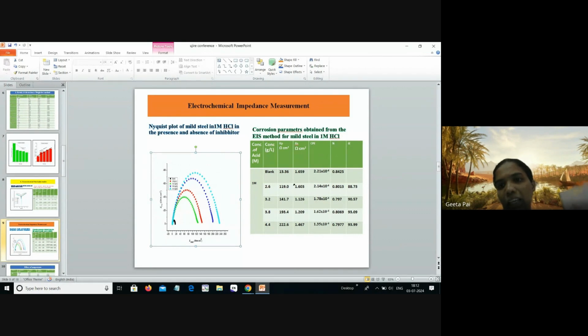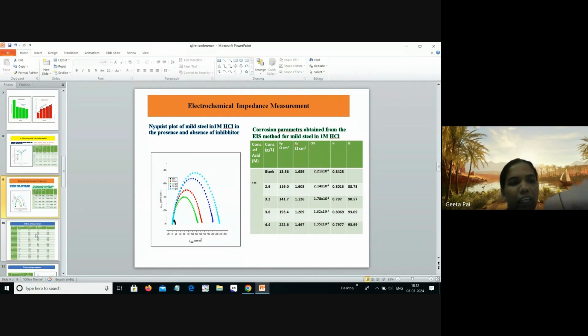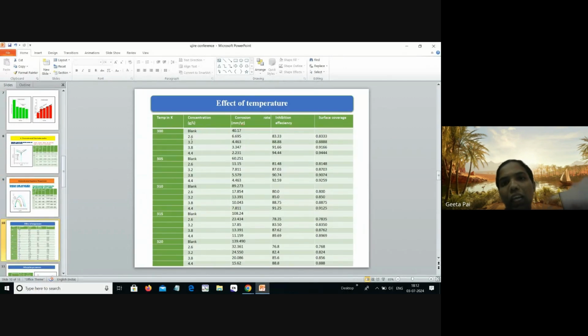Also, as the inhibitor concentration increases, the CPE value decreases. It means that the water molecules as well as H+ ions, which are adsorbed onto the metal surface, are replaced by the inhibitor molecules. As a result, inhibition efficiency goes on increasing. Then it can be further confirmed by the effect of temperature method.